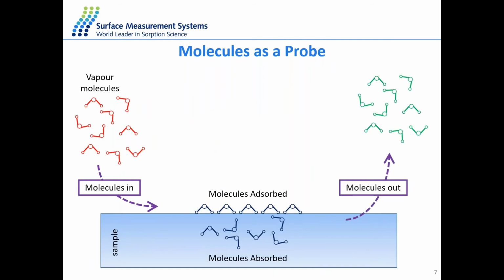So when we talk about a molecule interacting with a solid, it will be either adsorbed on the surface of the material or absorbed into the bulk of the material. By studying the kinetics of the sorption and the desorption, we can then easily predict some behavior of this solid sample at a certain temperature and relative humidity. And then we can calculate properties of this sample, for example, the BET surface area, the stability of the material, or the shelf life of this material at certain conditions.